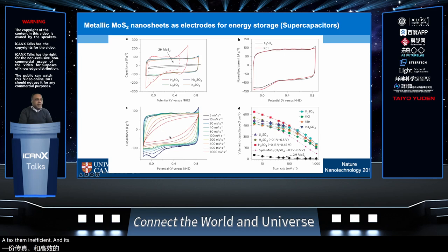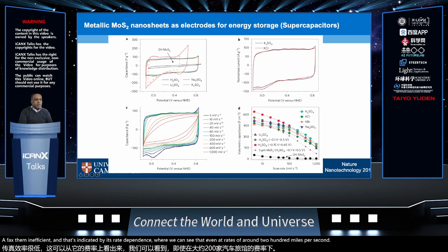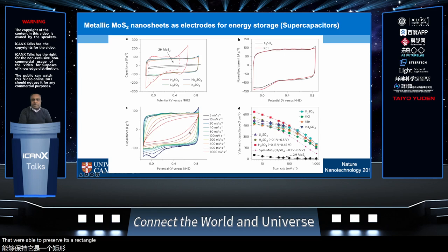And that's indicated by this rate dependence, where we can see that even at rates of around 200 millivolts per second, we're able to preserve the rectangular CV characteristics. And so we can summarize our data in the storage capability of these electrodes in the form of volumetric capacitance as a function of scan rate. At low scan rates, we're able to achieve volumetric capacitance that's quite high. There are other electrodes that have reported higher values, but at the time, this was quite reasonable.